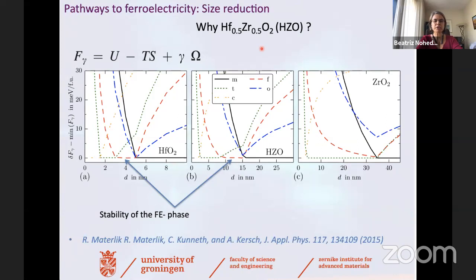Now, soon it was found that not only doped hafnia was interesting, but actually a particular composition with hafnium oxide and zirconium oxide mixed in equal ratios was very interesting and maybe better than hafnia. And that was also another question: why is that? Why does this particular composition happen to be very good? And this also had to do with the size effect.